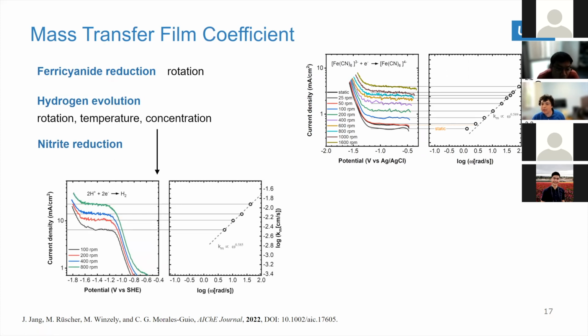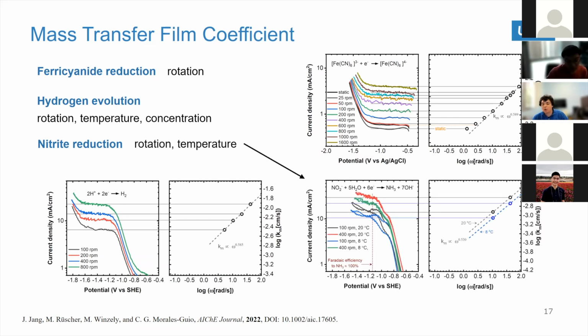So we control the pH in the bulk, we change the mass transport, and we look at the limiting current, and that gives us the Km value for protons. The Km value changes with the RPM, but the Km values will be different for ferricyanide or protons or nitrite. That is simply because all these different molecules are riding the same waves, the same hydrodynamics, but each molecule has intrinsically a different diffusion coefficient. And so even inside of those waves, they will move faster if they have a higher diffusion coefficient. So we can also do this with nitrite reduction.